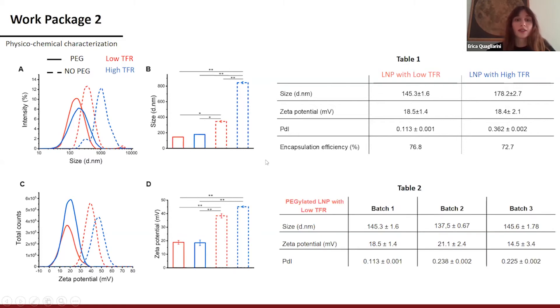So the second effort was to assess the efficiency of the microfluidic device by performing size and zeta potential measurement on three different batches of the same PEGylated nanoparticles generated at low total flow rate. As can be seen, all the values are similar, confirming the high reproducibility of this platform.